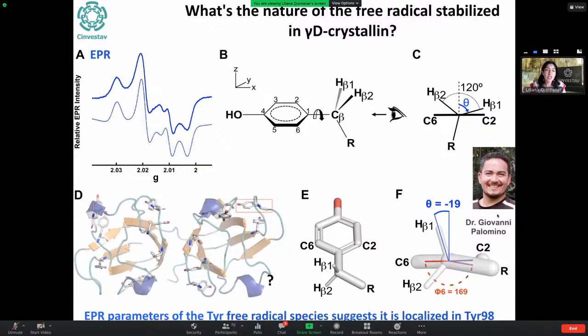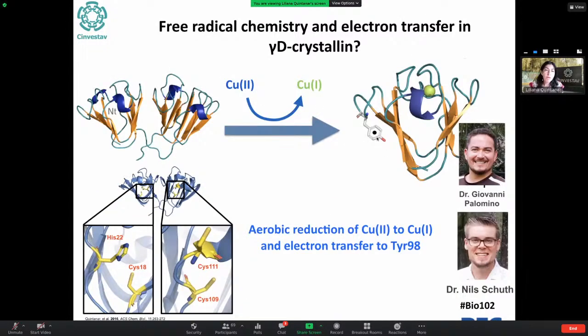And also, very briefly, to show you the EPR signal of the free radical in gamma D, we can extract the parameters and actually figure out which is the tyrosine that has the right angles, the right orientation to yield these EPR parameters. And we know it's tyrosine 98. So basically the summary is we have this protein that binds copper-2. Copper-2 is causing aggregation, but there's also this redox process. We have some idea of what these binding sites in the N-terminal domain will be, this histidine and this cysteine. But in the C-terminal domain, we have this motif with two cysteines that is really reminiscent of intracellular copper chaperones. And this is happening under aerobic conditions.